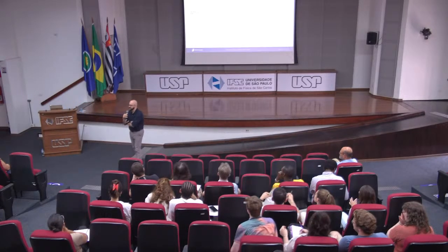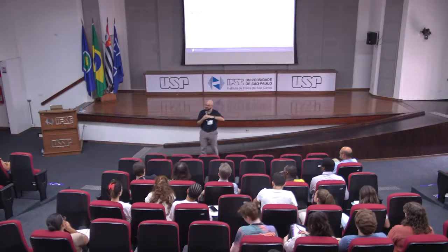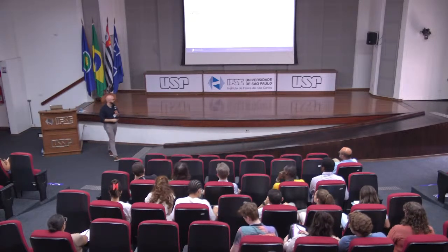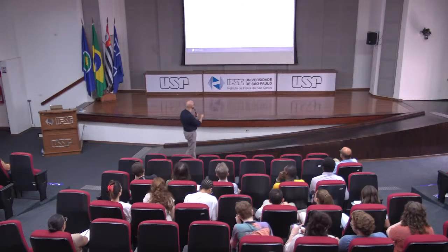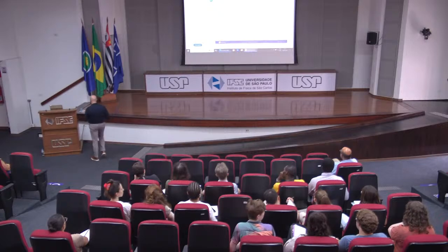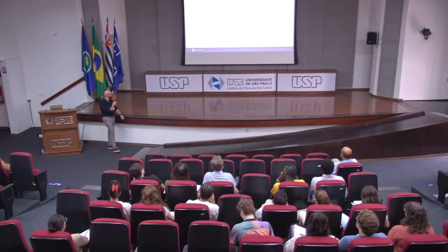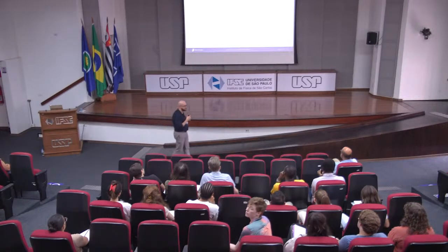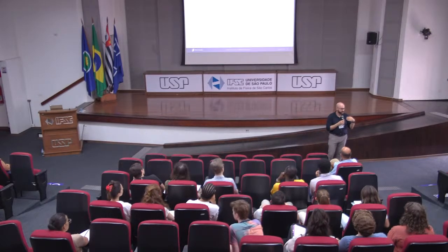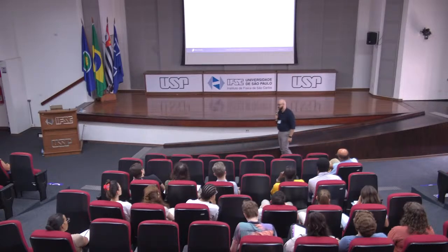I think the mobility is less important, and the number of effective charge carriers is more. What pushed me in this direction is the large change with composition that you see. I don't think I made that clear, because I was moving a little bit faster. Here, on the left graph, the ionic conductivity changes by 3 orders of magnitude as I change the composition from 0.2 to 0.5. I do believe that to change it by 1,000, it does not make sense that the mobility would be changing. The ions would be moving 1,000 times faster, for example. So I do believe it is the number of effective charge carriers.